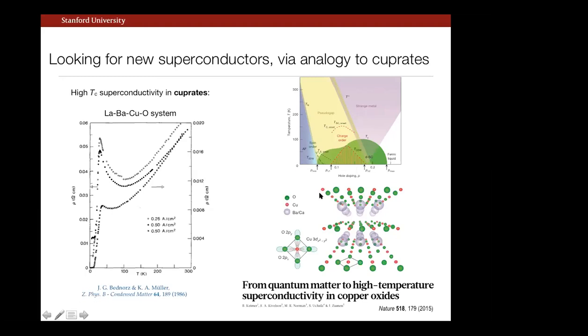The second thing that I will emphasize here is the crystal structures. There are many, many of them now, with different stacking motifs, but the common ingredient is a quasi-2D crystal structure composed of copper oxide planes and various stacking sequences with rare earth spacers and so on. So it's well understood that the relevant electronic states near the chemical potential are hosted in the copper oxide planes. And in particular, one of the important notions for hole doping in the system is the so-called Zhang-Rice singlet.